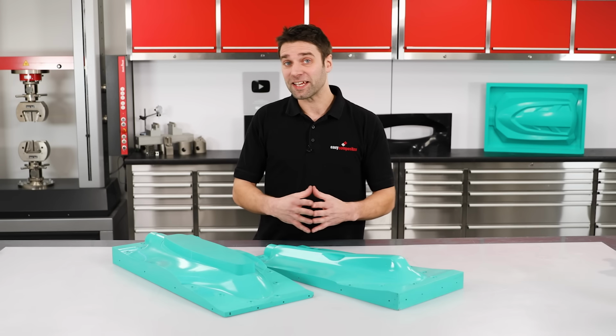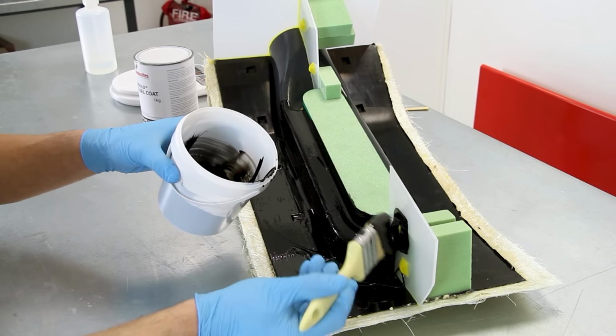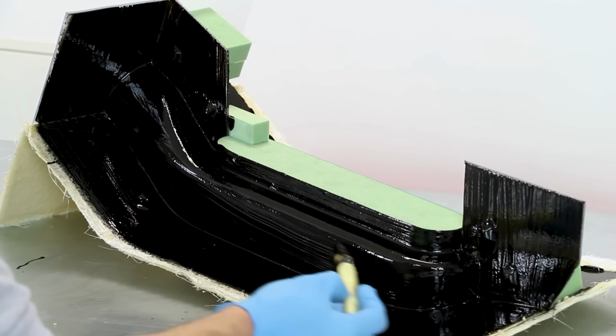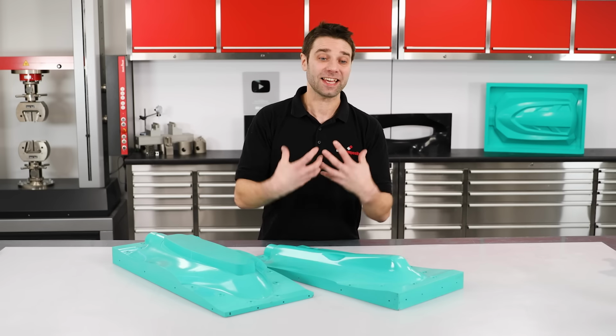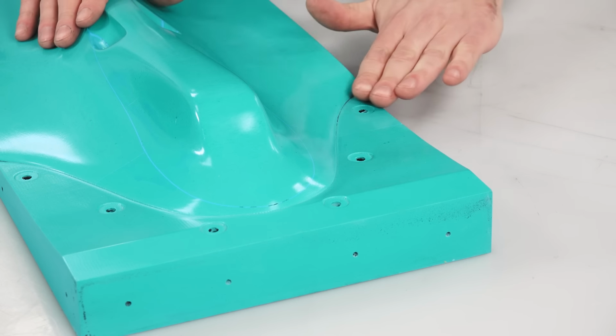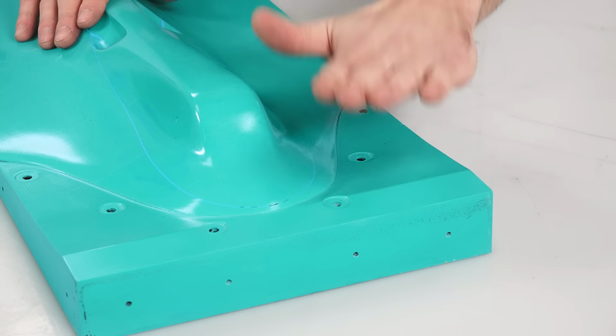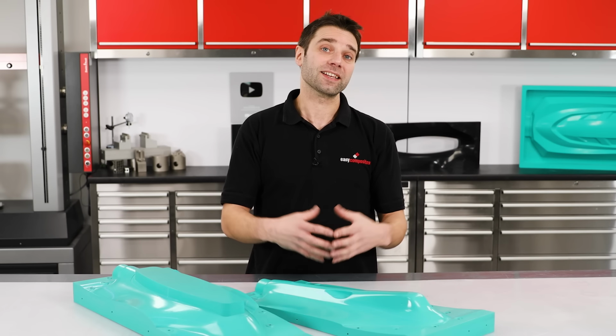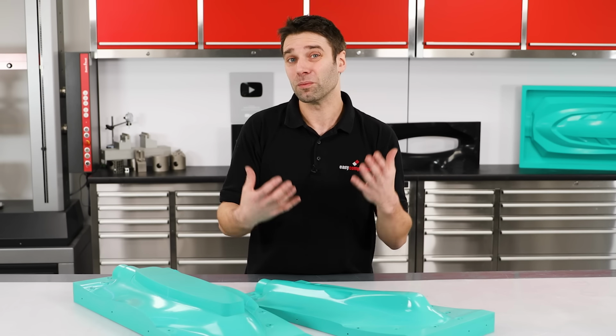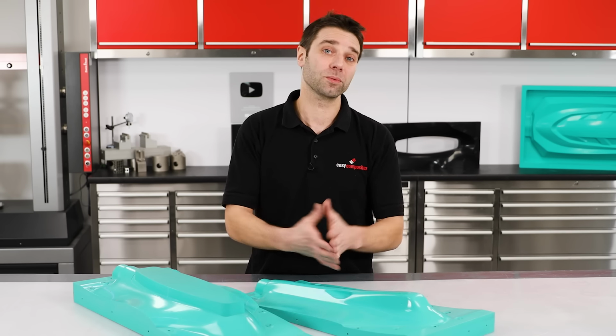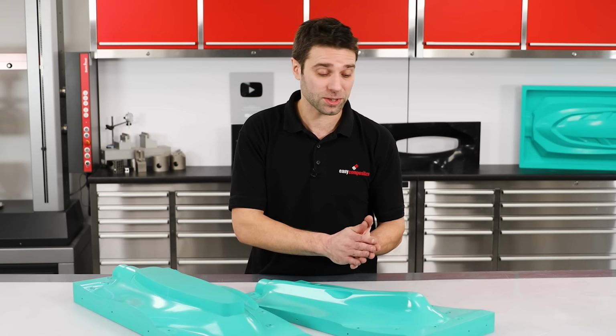Unlike creating hand laminated split molds, where your pattern will typically be in one piece and then you attach temporary barriers onto them and form your parting lines against that, in the case of prepreg patterns, you will nearly always have those features machined in. The reason for that is that the temporary barriers simply won't withstand the heat and pressure that will be applied to them during a prepreg cure cycle.